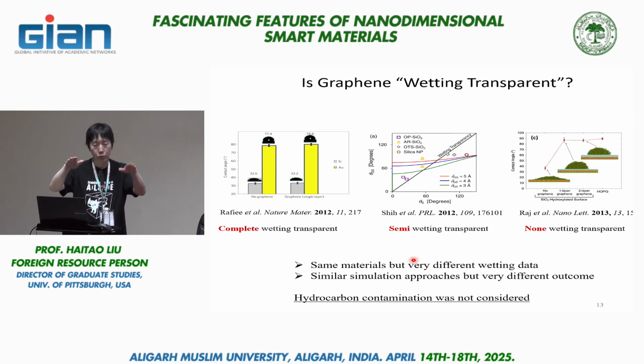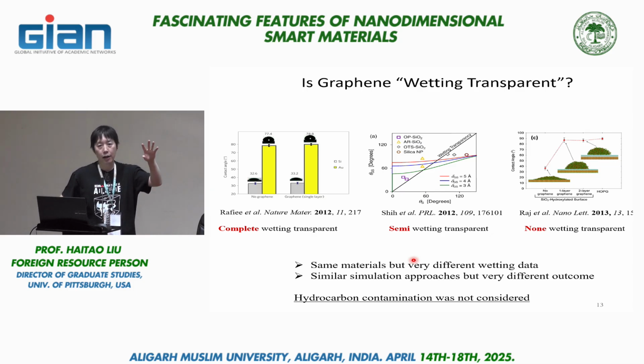What you may recall is yesterday I showed two different wetting data. One is graphene on copper, another is graphite. If you think about graphite, you can view it as a single layer graphene on top of a graphite substrate. So you have two different substrates of graphene. One is a copper support, another is graphite support. If you look at the wettability data, after they got contaminated in air, their water contact angles are almost the same, 90 degrees. But before they were contaminated by air, the graphite contact angle is around 62 or 65, and the graphene on copper is around 45. So what that means is water droplet sitting on graphene, they can actually feel what is beneath graphene. And that idea is called wetting transparency.